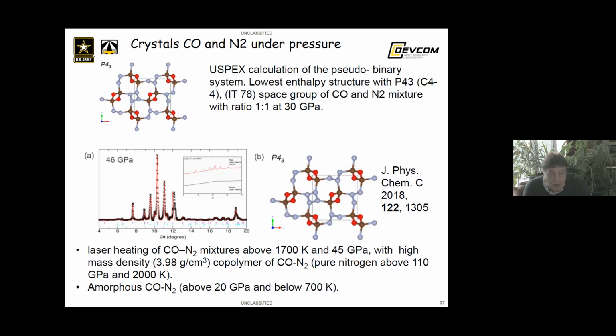This is comparable with cubic gauche density. Let me remind that pure nitrogen requires pressure about 110 GPa and heating up to 2000 K. Significant lowering of the pressure and temperature, isn't it? Amorphous CON2 could be obtained even below 700 K at 25 GPa. Remember our analysis of amorphous network of CON2, adding a carbon monoxide significantly lowered the transition pressure to polymeric structure.